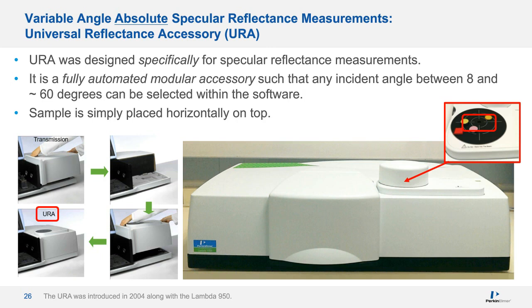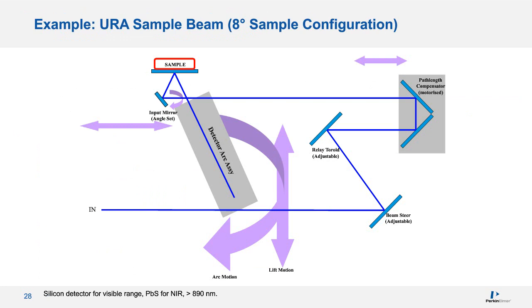So what's going on inside the URA? How does it actually work? In this slide, you can observe the sample, highlighted in red at the top, placed horizontally. The URA contains a small slit on top. The sample, typically an inch in diameter, is placed over this slit such that a square beam of light, roughly 5 by 5 millimeters, is directed by the input mirror upwards to interact with the sample. The light then leaves the sample and hits the detector at an angle that is equal to the user-defined incident angle. Thus, a specular reflectance measurement is performed.